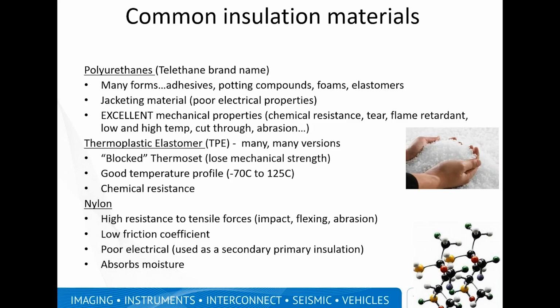We do have our thermoplastic elastomers. These are our TPEs. These are part of the olefin family, so we want to be aware when using these materials there could be some adhesion concerns. They are very difficult to mold to, but you do have a great temperature profile of -70 degrees Celsius all the way up to 125 degrees Celsius. So when you look at that temperature range and compare it to some of the other thermoplastics, it's probably the widest temperature range that you can get in a thermoplastic. Because it is an olefin-based material, it has great chemical resistance properties. Generally, the durometers on these TPE materials can range from 65 Shore A all the way up to 90 Shore A, which means it's a very flexible material.